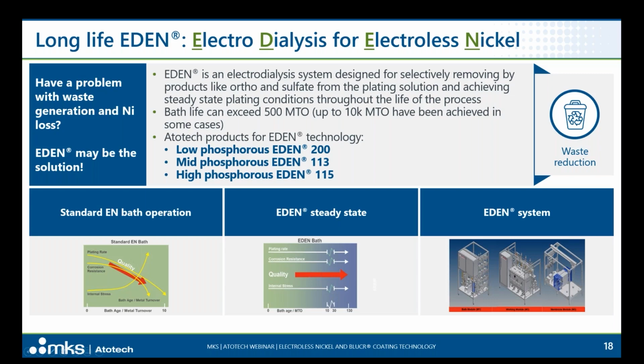In our Atotech product range, we offer the whole range of phosphorus incorporation in the coating. So low P electroless nickel for Eden is the product Eden 200, mid P electroless nickel Eden 113. In case of high P, we have Eden 115. Also, it's good to know that by using the Eden technology, we can considerably reduce the waste due to the increased bath life.